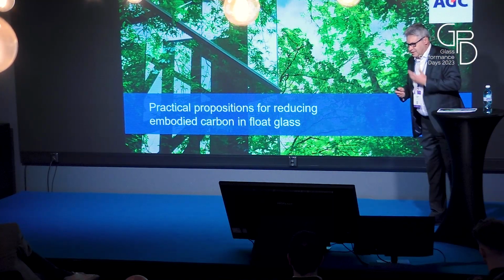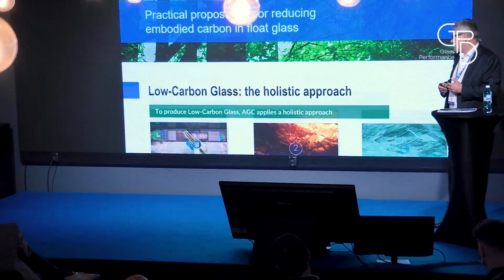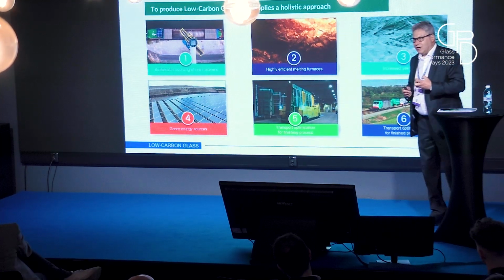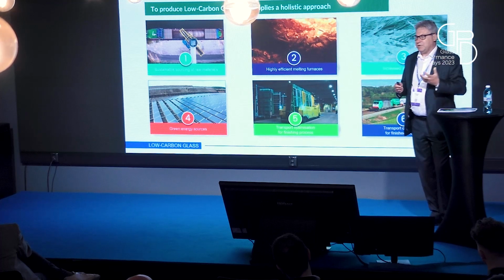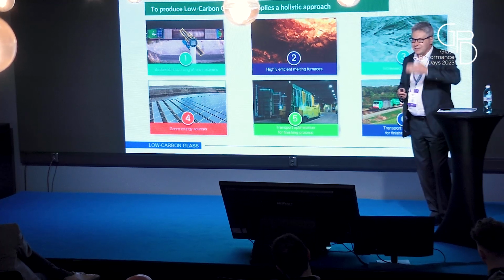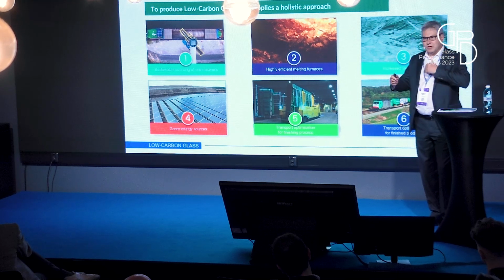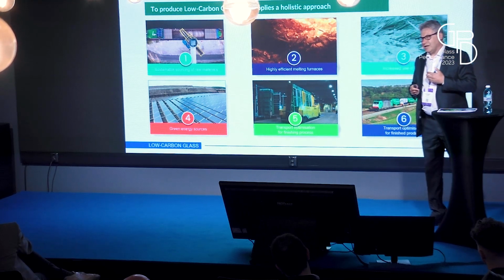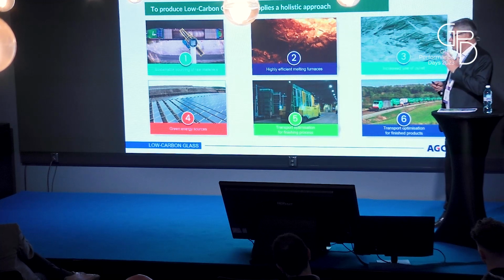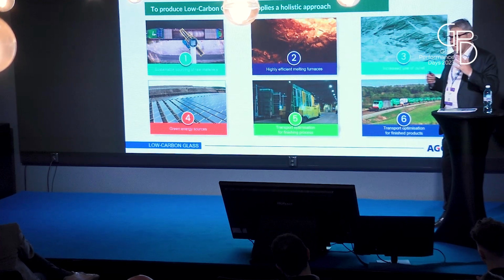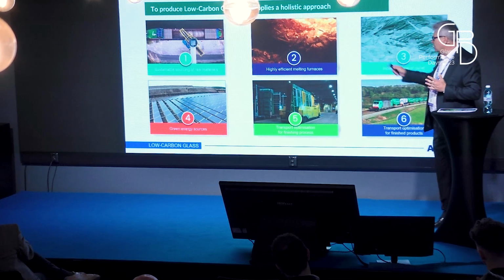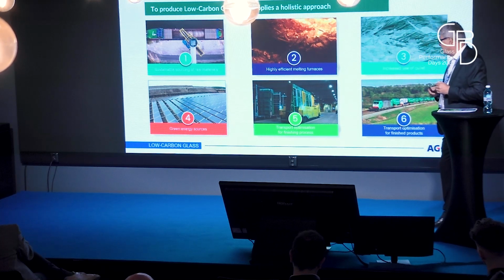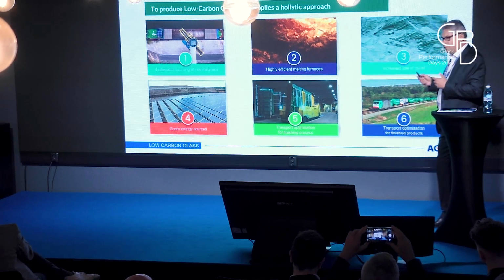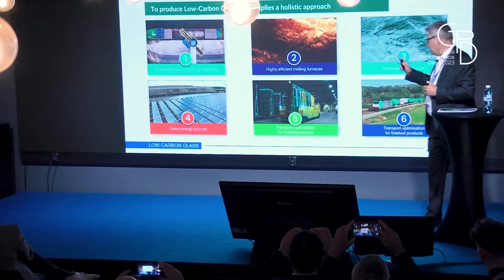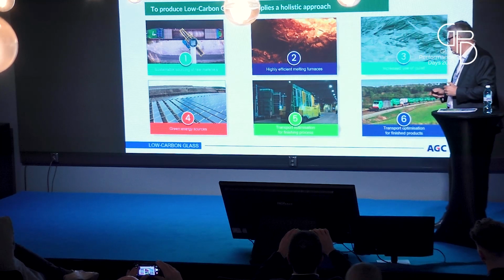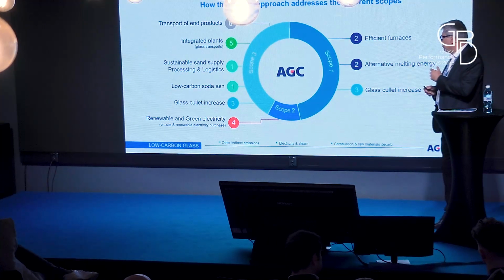So what we propose and do. First, we don't want to rely only on cullet. Of course, people think, okay, we put more cullet, let's say close to 100%, it will be fully recycled material. We decided, for different reasons that I will explain, not to have only cullet, but to rely on 6 different pillars. You saw the raw material, the furnace, and of course the cullet, which will be a very important part, but also green energy, transportation, and optimization. So let's go point by point.